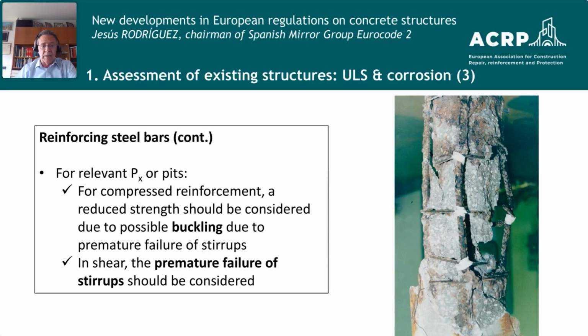And this is, I believe, my last presentation on this part. For the case of possibilities of premature failure of stirrups due to corrosion, stirrups are the thinnest reinforcement, we need to consider in compressive bars the possibility of buckling, and in the shear behavior, the possibility that a premature failure of one stirrup can allow the shear crack to be produced with a reduced strength in shear.